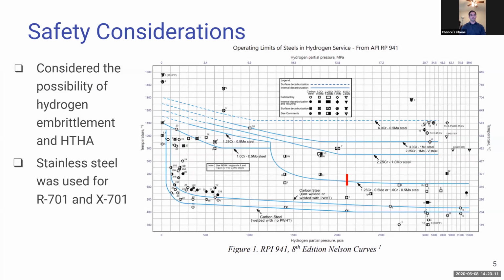For safety considerations, we wanted to look at the possibility of both hydrogen embrittlement and high temperature hydrogen attack. It seemed like the high temperature hydrogen attack was the only real threat to our unit. And so shown on the graph on the right, you can see the red line depicts the operating range of our unit. Depending on what temperature we use for the reactor, it could be anywhere on that line. And you can see that line is well above the minimum that the carbon steel is rated for. So moving forward, we decided to use stainless steel for both our reactor and that first heat exchanger right after the reactor, so that way we don't have any high temperature hydrogen attack occurring.